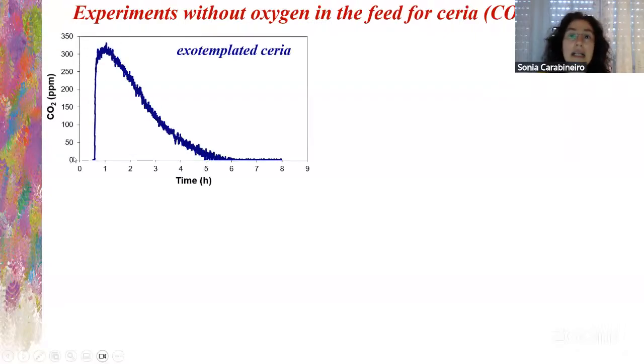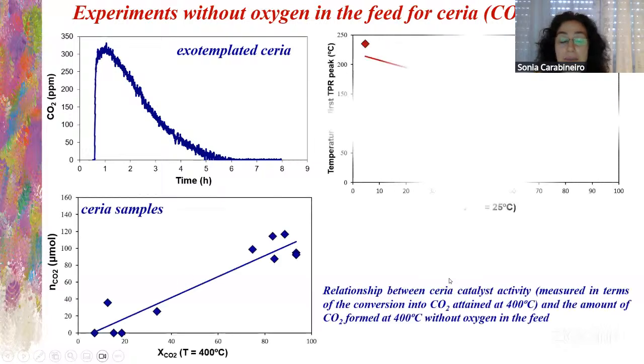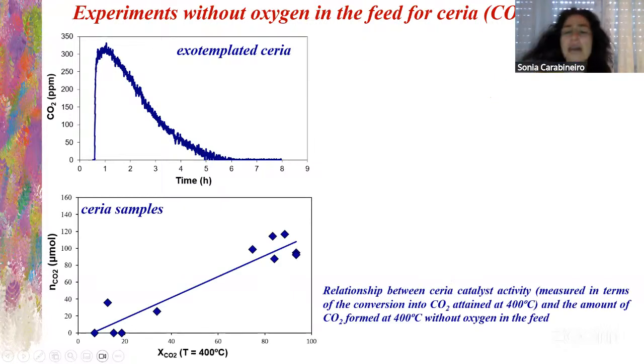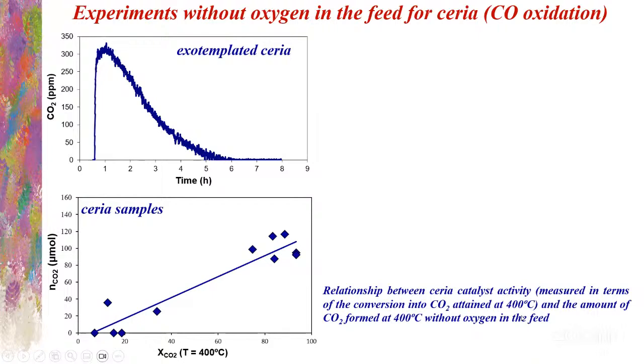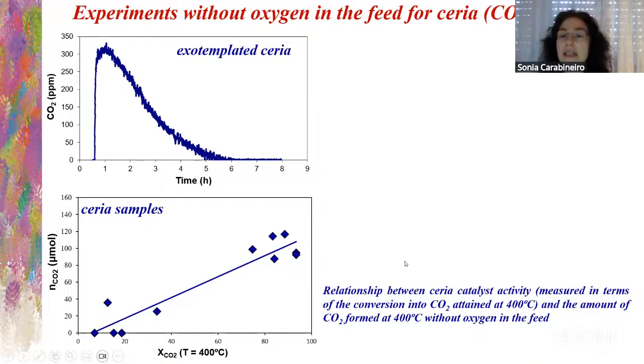And we see here, without oxygen being supplied, this CO oxidation takes place because CO2 is being formed. Then it decreases. Why? Because the oxide surface is free from oxygen. It's being reacted with CO, so it eventually decreases. So we found a relationship between catalyst activity measured in terms of CO conversion into CO2 at 400 degrees and the amount of CO2 formed at 400 degrees without oxygen in the feed. So we can see here a relationship.